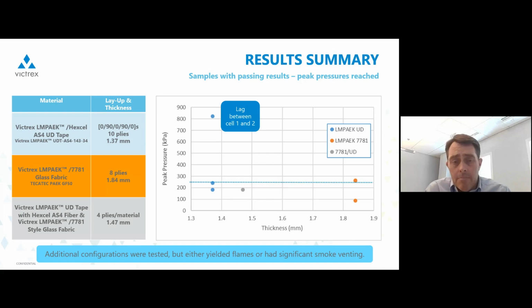We did test a number of additional configurations, but those were all thinner. So I'd mentioned that we did 4, 8, and 10 plies for the UD. The 4 and the 8 did fail. They did have something going through the laminate, whether it was smoke or flame. Similarly, the thinner glass laminates that we tried, the 4 and the 6, also had that. Next one.